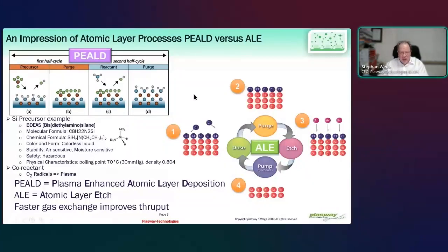On the other hand, and this was my idea, ALD was developed since the 60s, 70s, especially in Finland, and we are now in the phase where we would like not just to do atomic layer deposition, where each step brings one atomic layer onto the surface of your wafer. When you would like to remove material, which people also want to do, you have a similar approach. For example, to etch silicon, you can apply chlorine, but here you already need a plasma to create the chlorine that then sits on top of the silicon. At normal temperature, this chlorine will not react with the silicon. You also need a purge step to remove the remaining chlorine out of the chamber.